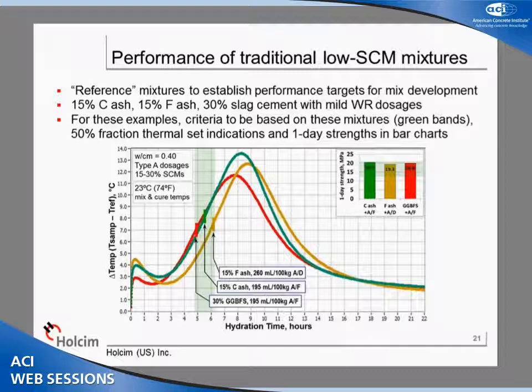And we're establishing thermal profiles that will allow us to establish a target band, if you will, this shaded band that will give us a reference for future use in the development of a concrete mix design that will perform in a roughly equivalent fashion. Also, the one-day strengths, we can do the same thing and come up with somewhat arbitrary, but at least a minimum strength requirement target for our one-day paste mixtures going forward.